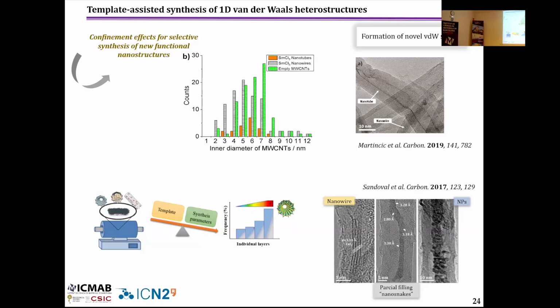Okay, thanks. Hi, Stefania. Have you tried to fill the carbon nanotubes with metal oxides? Is it possible? Yes, usually for filling with metal oxides, the techniques that are used are in situ techniques. You can also use a precursor, another precursor, and then oxidize it. This is also possible. But in general, filling carbon nanotubes with oxides is done by CVD or arc discharge or other in situ approaches.